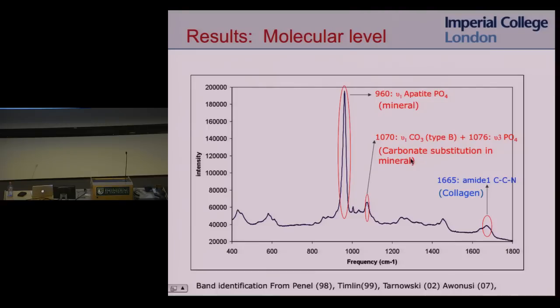Each peak represents a different component of the bone. This big peak here is the apatite, which is the mineral. This peak here is some carbonate that gets substituted into the mineral that you can start to detect. And these peaks out here are due to the collagen. So we can take this spectrum and we can do some univariate analysis, which means looking at the peaks themselves, measuring the peaks, what's the area under the peak, what's the width of the peak, and then compare those for the different groups of mice.